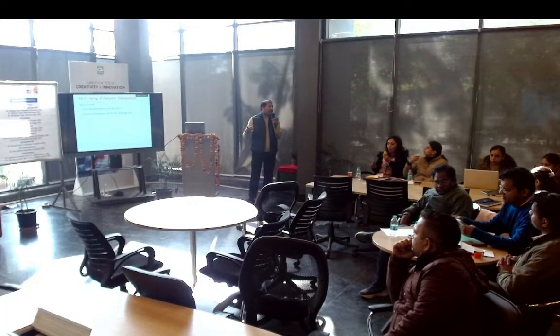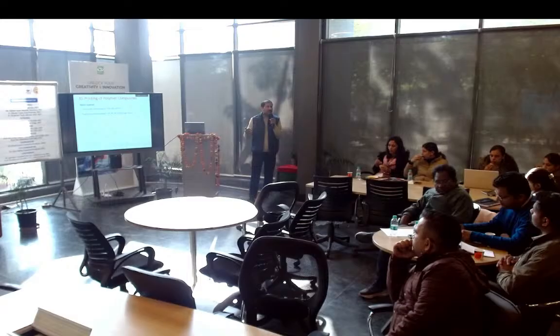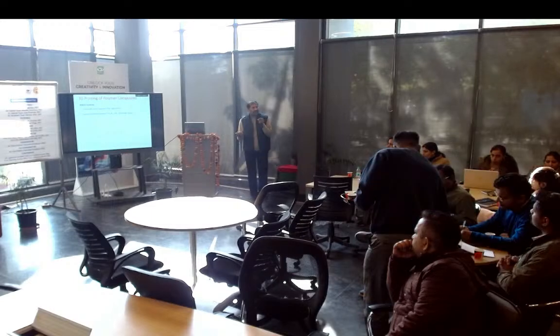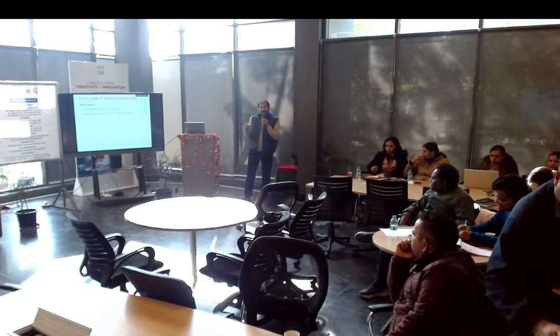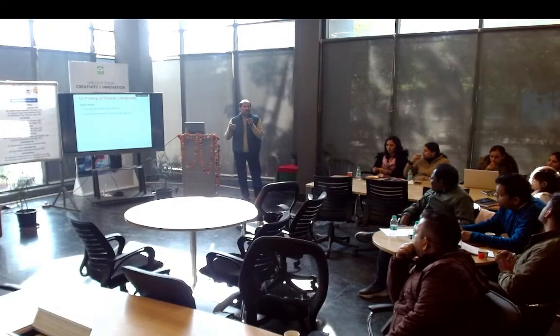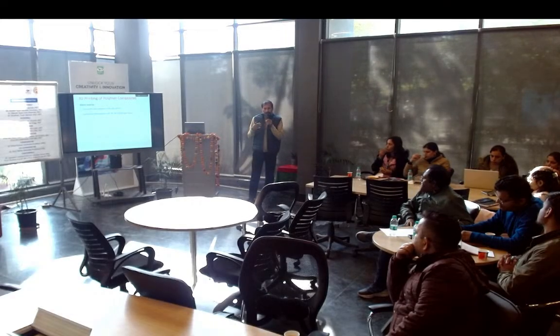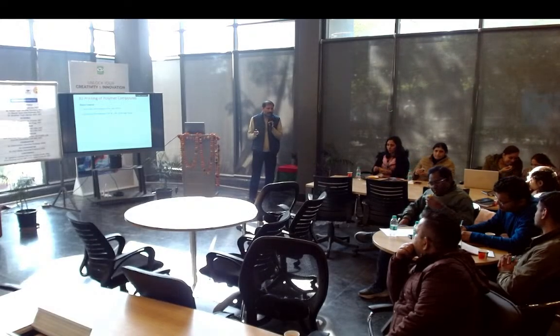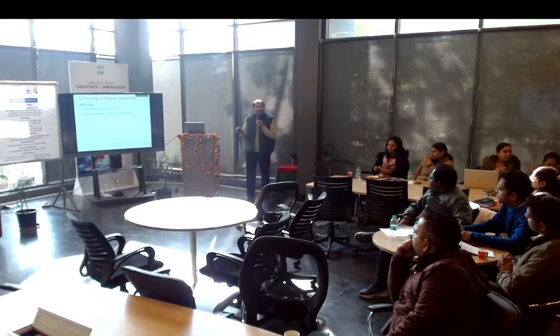It is 60 degrees Celsius. So on the rise of the temperature of the working environment, it also absorbs humidity and moisture from the atmosphere, so it deteriorates properties and accordingly functions. But PLA is very print friendly. Anyone who wants to try 3D printing, PLA should be the first choice, because it is very print friendly and not temperature sensitive; you can print it by opening the door or top of the machine. While ABS is difficult to print. You have to close the chamber and maintain the temperature because these materials are temperature sensitive. They will warp, curl or deform.